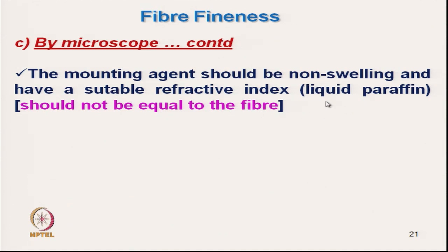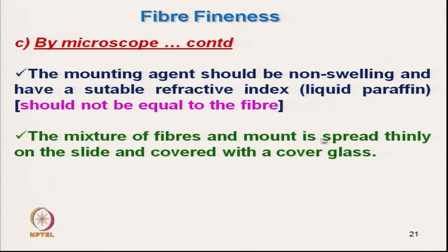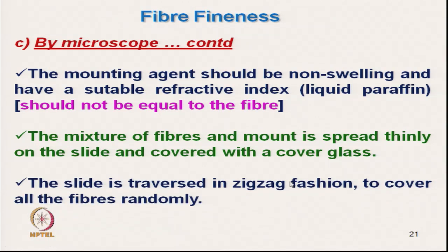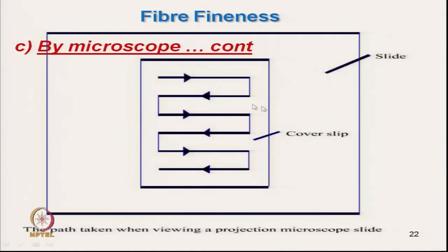Typically liquid paraffin is used, and the mixture of fiber and mount is spread properly on the slide and covered with the cover glass, and the slide is moved in zigzag fashion, so as to cover most of the fibers randomly. So, this is the way the slides need to be moved.